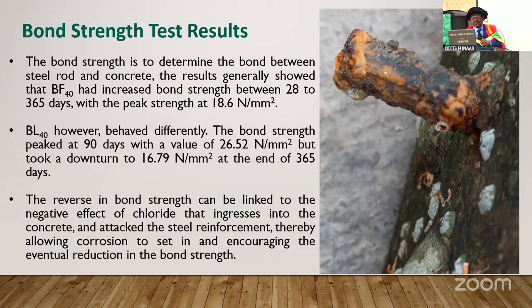The result generally showed that BF40 had increased in bond strength between 28 and 365 days with peak strength at 18.6 MPa. BL40, however, behaved differently. The bond strength peaked at 90 days with a value of 26.52, but took a downturn to 16.79 at the end of 365 days. The reversal in the bond strength can be linked to the negative effect of chloride that ingressed into the concrete and attacked the steel reinforcement, thereby allowing corrosion to set in and encouraging the eventual reduction in bond strength.